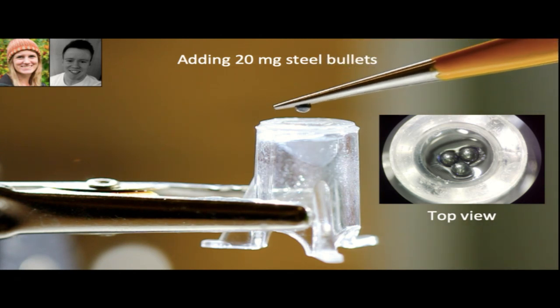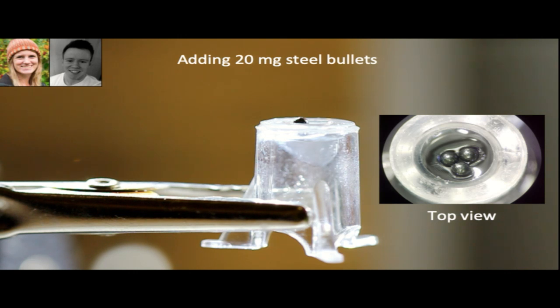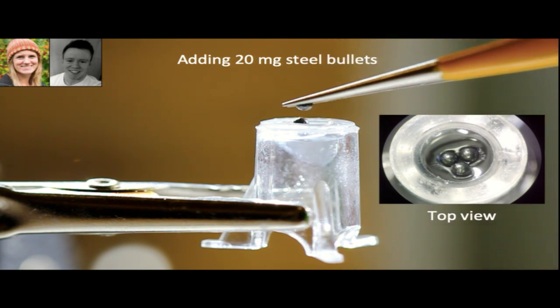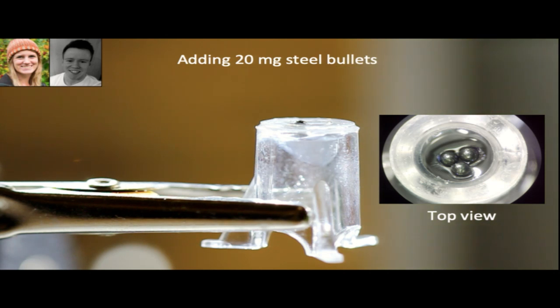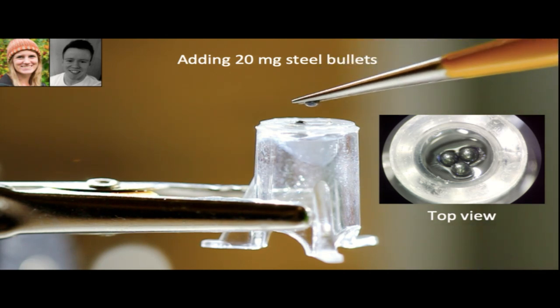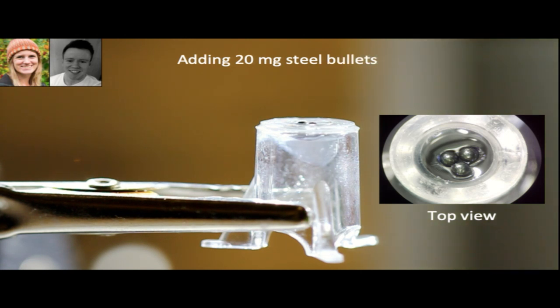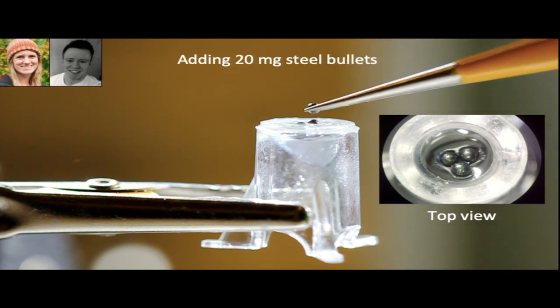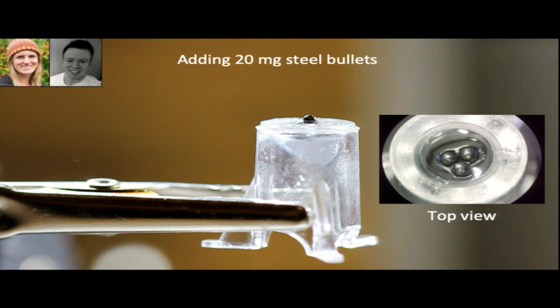And then you count them, OK? 20 milligrams. Now you can see the film here. See, it starts moving when you load something. 60. 80. 100. This is only 200 nanometer thick, eh? So this is extremely strong. Oops, now it breaks. And the load cell just caught this one before it disappeared. So we have an extremely strong, extremely thin layer.